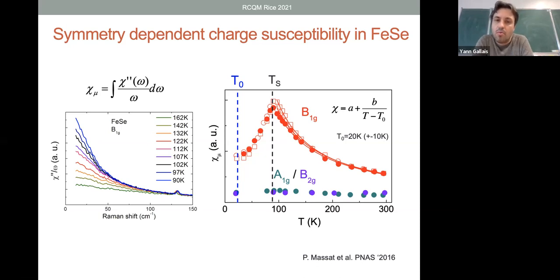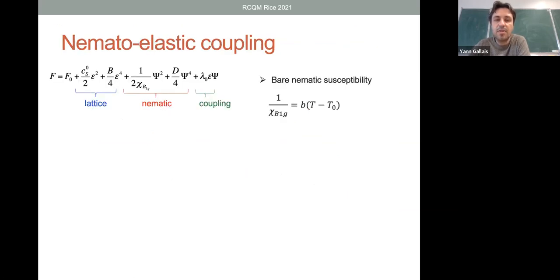So the one important aspect of this Curie-Weiss dependence is that even though the susceptibility peaks at TS, clearly, the Curie-Weiss temperature is actually located at a lower temperature, T naught. So there is a distinction between TS and T naught. This is the same distinction for people who are used to elastoresistivity, but for people who are not familiar with this, let me explain briefly what the difference between these two temperatures means.